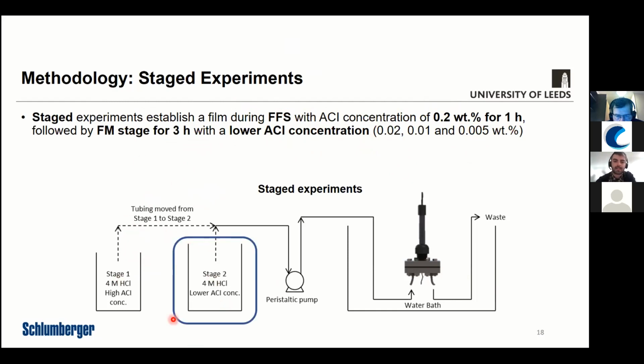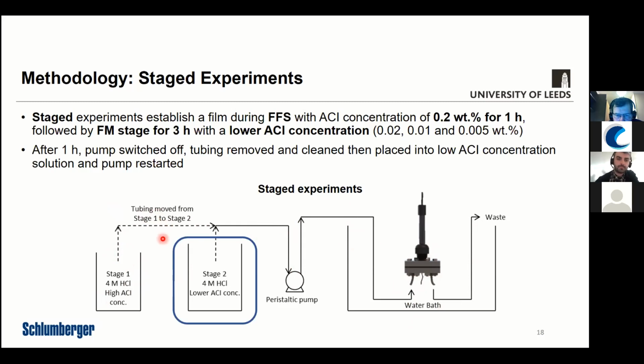So in this particular case, we've now added a second beaker in there. So for the first stage, we would have the 4 molar hydrochloric acid, 0.2% solution. We'd have the tubing, again, pumping, using a peristaltic pump the solution through and into the waste. After 1 hour, we would switch the pump off. We'd remove the tubing and wipe any remaining acid off the surface of the tube, immerse it into the stage 2 beaker, which would contain the same hydrochloric acid, but a lower inhibitor concentration. And then we would restart the pump.